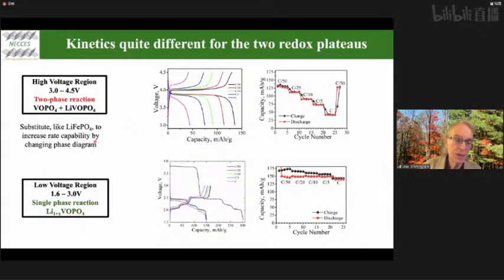In total contrast, however, in the low voltage regime, that's the regime down here, to study that, we first put one lithium in, then we put the second lithium in, then just cycle backwards and forwards for the second lithium. And you can see in contrast to the 4-volt one where we lost capacity as we increase the rate, here there's essentially no change in capacity whatsoever.